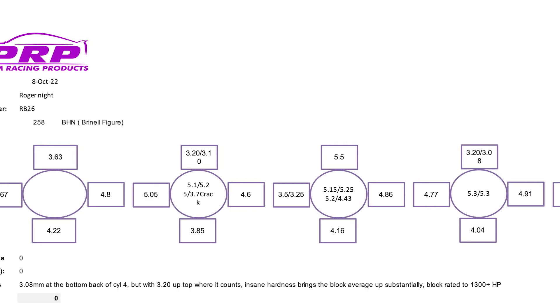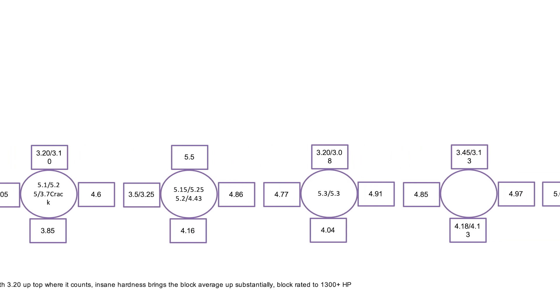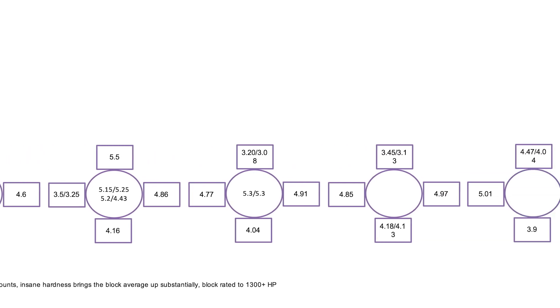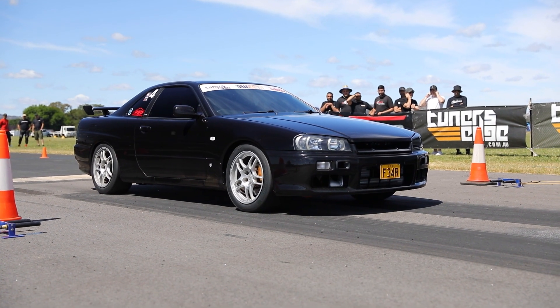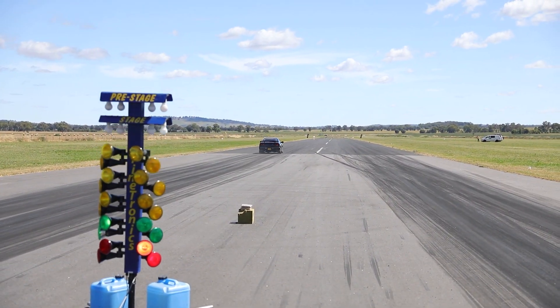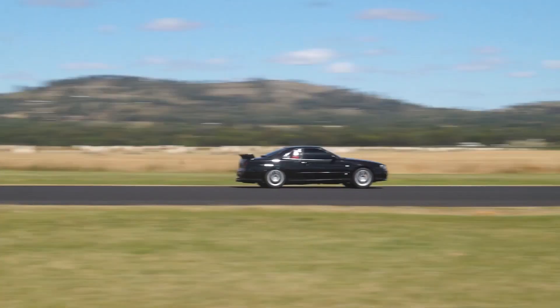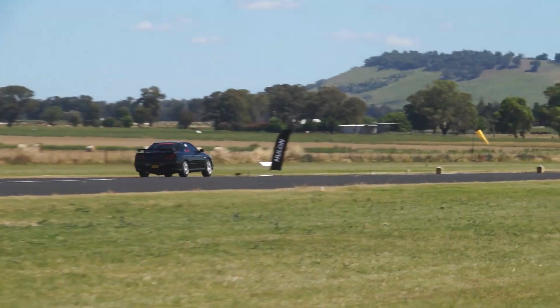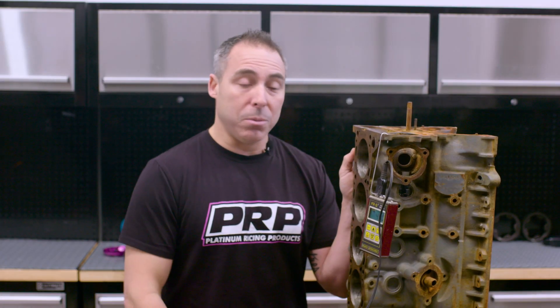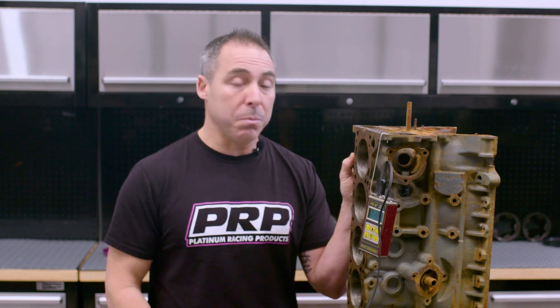So we've got three and a half mil on one side of the crack and four and a half mil on the other side — a one mil differential on either side of that crack, which goes to show we did have a fault line through there. After testing the rest of the block, we can't find anything less than about 3.2 millimetres anywhere. It was sitting mainly at 1100 horsepower, creeping up to 1200-1300 with the big dirty shot of nitrous. It's got to have been close to 1500 horsepower — who knows what that turbo was maxed out at plus nitrous — but that's what it took to break this block.